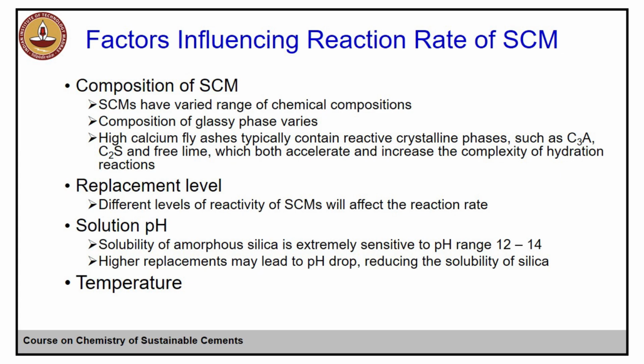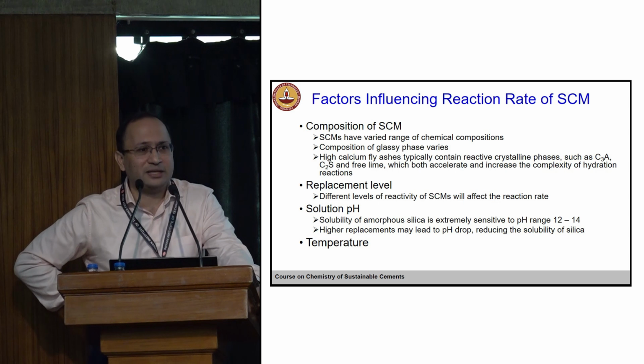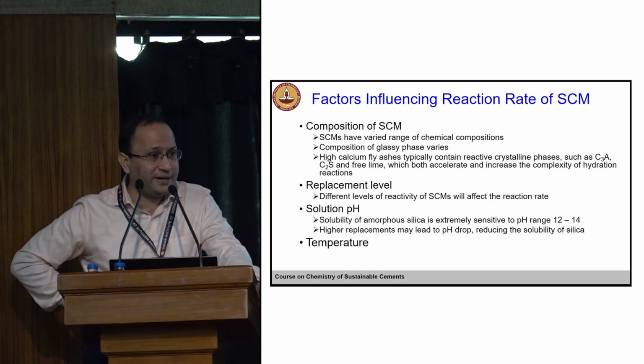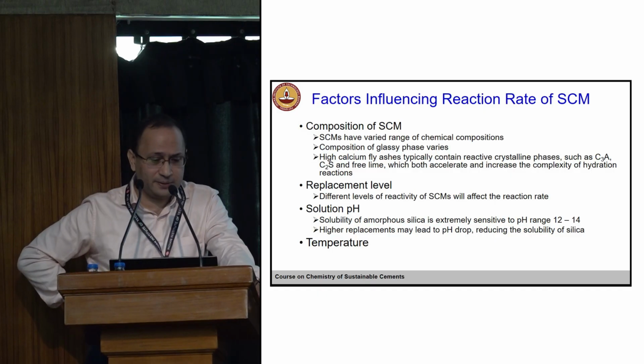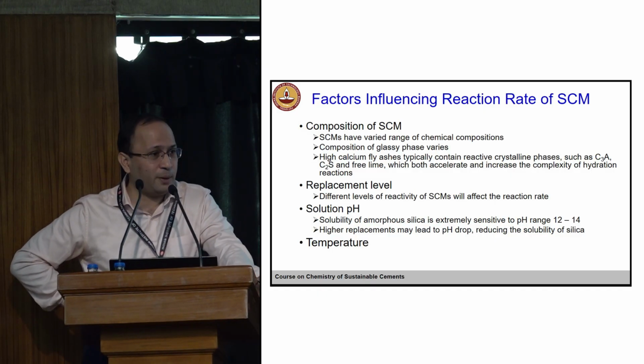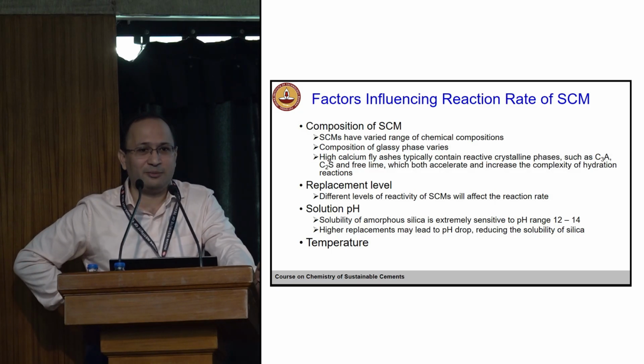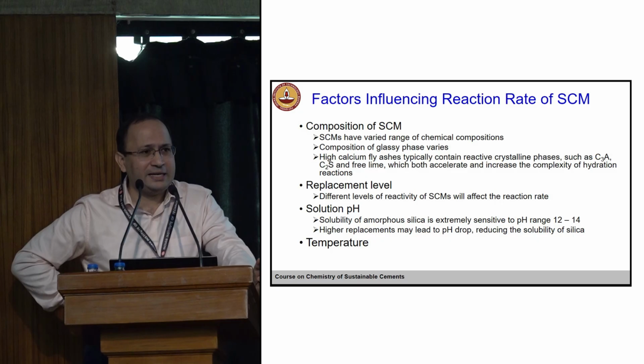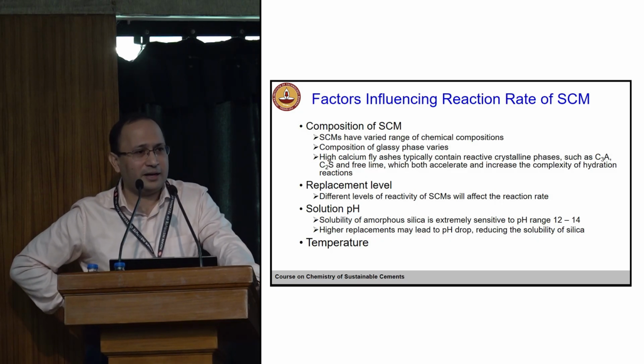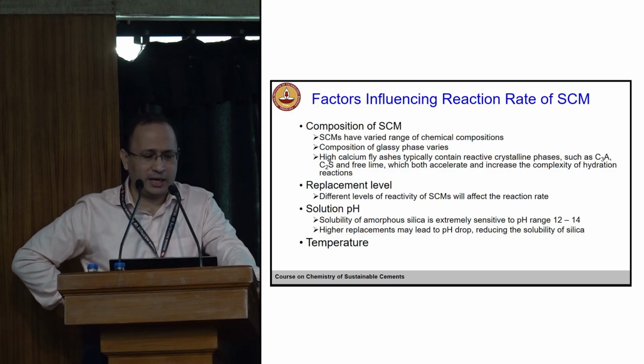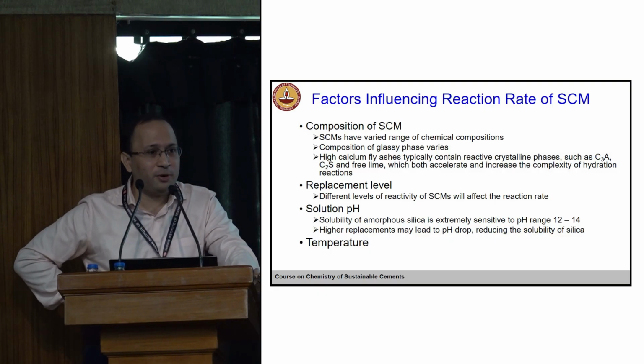Okay, so now if we dig deeper into SCMs, right? Eventually we would like to understand how reactive these SCMs are. Obviously, the composition of the SCM will matter, right? It will determine its reaction rate. And we know that SCMs have a varied composition, as I showed in the ternary phase diagram, right? It can have alkalis, it can have more silica, it can have less iron, more iron, depending on the source. The amorphous phase itself may change, the composition may change, and we know that it's the amorphous phase, or glassy phase, which will govern the reactivity of a particular SCM.